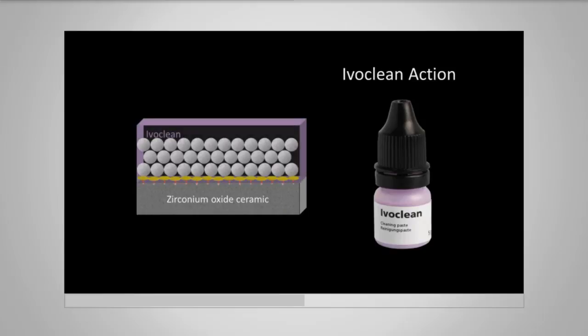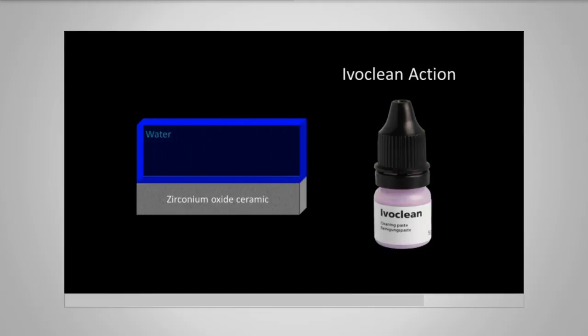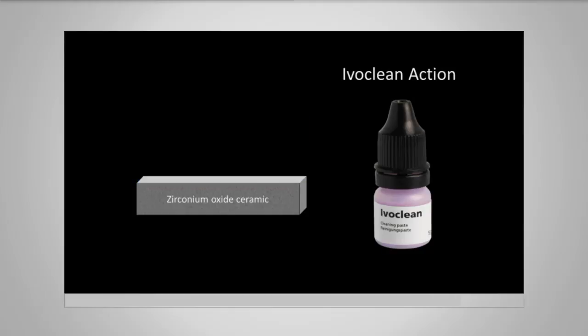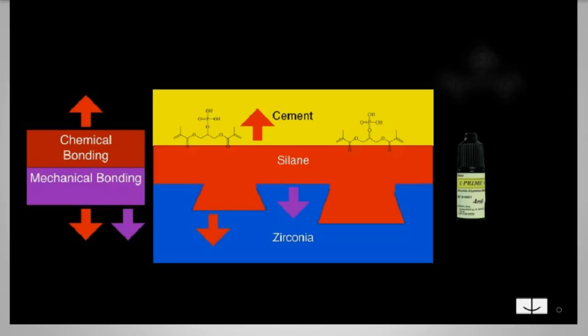So you wash it off. But what happens with the Ivoclean is that Ivoclean is pure zirconia. It is liquid zirconia. And so if you wash it with Ivoclean, then the phospholipids have a higher affinity to the liquid zirconia. They come off the zirconium oxide ceramic onto the Ivoclean. Then you can wash that off, leaving all the sites now open and ready for your zirconia-specific primer, all those phosphate groups, and then you can put your resin cement right on top of that. All right? So that's how and why you use Ivoclean.